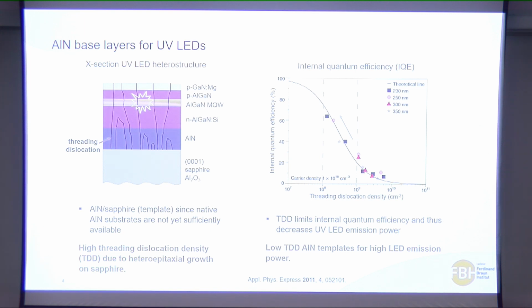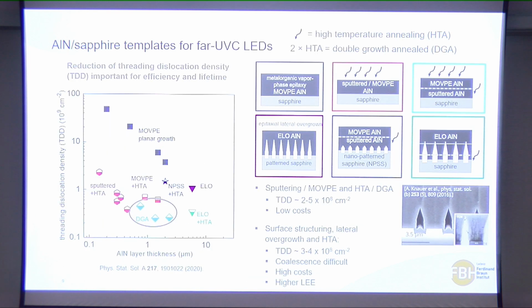And you see that if you reduce the threading dislocation density, you can get a very large increase in the efficiency of the devices. And for us, the number 10 to the 8 is an important number, because if you can reach there, then you already have quite a high internal efficiency. So there's a very stark increase as you go from 10 to the 10 to 10 to the 8. And therefore, we have developed many different technologies on how we can make such substrates and templates with a lower threading dislocation density.